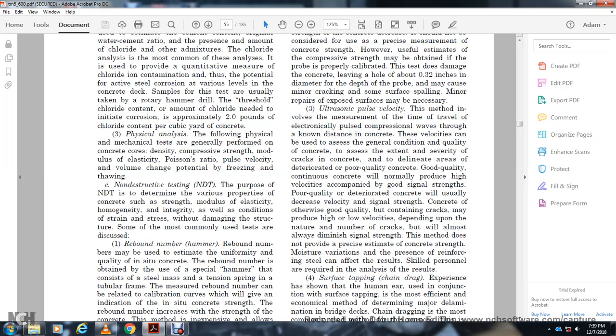Good quality continuous concrete will normally produce high velocity accompanied by good signal strength. Poor quality deteriorated concrete will usually decrease the velocity and signal strength. Concrete of otherwise good quality but containing cracks may produce a higher or lower velocity depending upon the nature and number of cracks, but will almost always diminish signal strength. This method does not provide a precise estimate of the concrete strength. Moisture variation and the presence of reinforcement steel can affect the result. Skilled personnel are required for the analysis of the results.